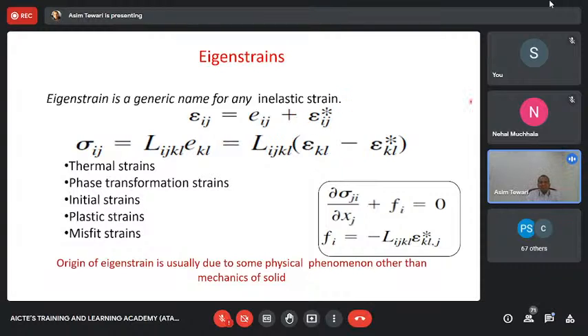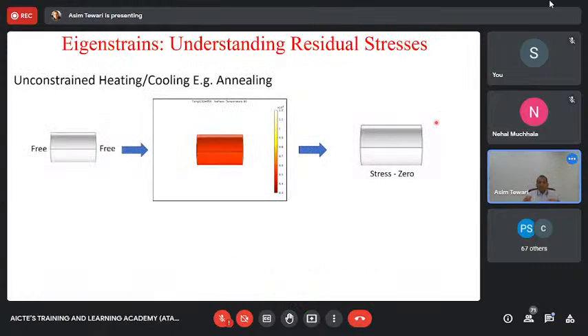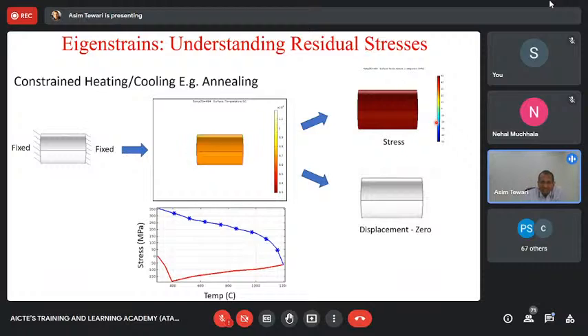So that is the basic understanding which you need to have: in the free case, the elastic strain was 0, and the eigenstrain was exactly equal to the total strain. In the fixed case, the total strain is 0 because you have it fixed. And because the total strain is 0, the elastic strain has to be equal to the opposite sign of the eigenstrain. And what is the eigenstrain? Eigenstrain is the strain because of the expansion because of heating. So eigenstrain is always a strain which comes from a physics other than the stress analysis physics. The stress analysis and solid mechanics is not adding anything to the eigenstrain. So the eigenstrain could be because of the coefficient of thermal expansion, phase transformation, twinning.